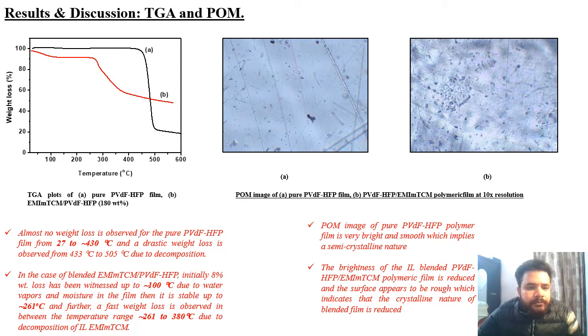In case of ionic liquid doped PVDF-HFP, first of all, till 100 degrees there is 8% weight loss, which is due to the water and moisture present inside the film. After that, it is stable until 261 degrees Celsius, and then there is a fast weight loss till 380 degrees Celsius. In the end, almost 50% of the film weight remains.